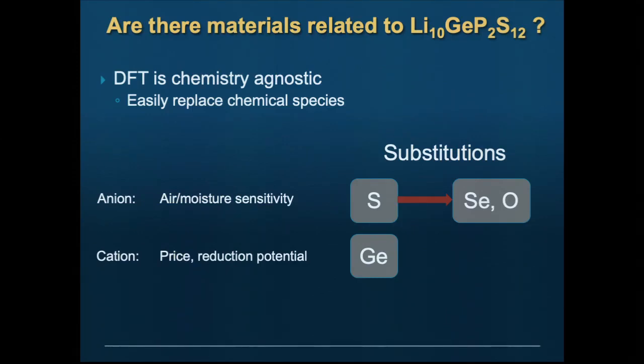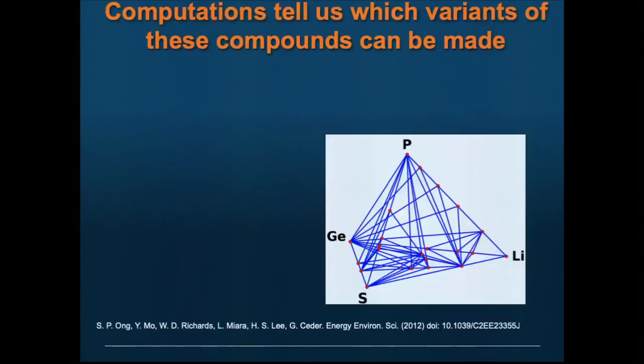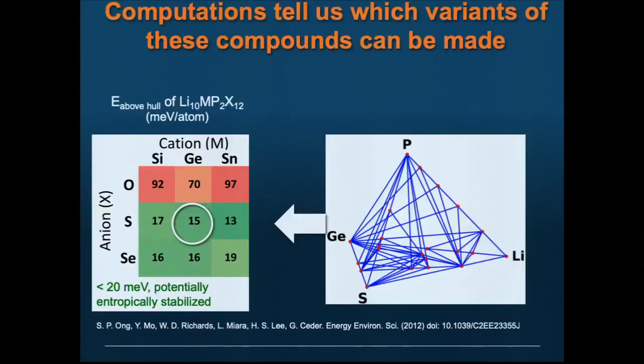So we wanted to see, could you replace it by selenium? Not that selenium is better, but if you could replace it by oxygen, that'd be awesome. And germanium is a non-starter because of price, right? Could you replace it by things in the same column, silicon or tin? This is a great ab initio problem, because you can first look at the stability of these compounds. So we calculate the substitutions with silicon and tin, and on the anion with oxygen and selenium, and we calculate the energy by which it's stable or metastable. And this is the compound that's been made.